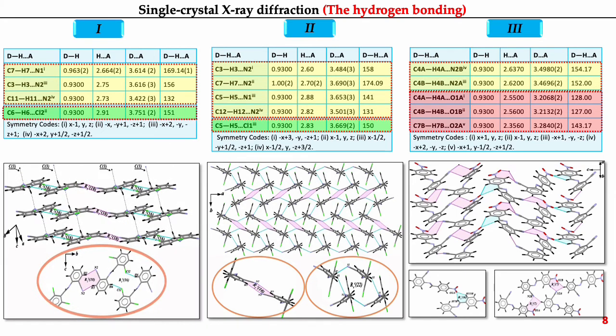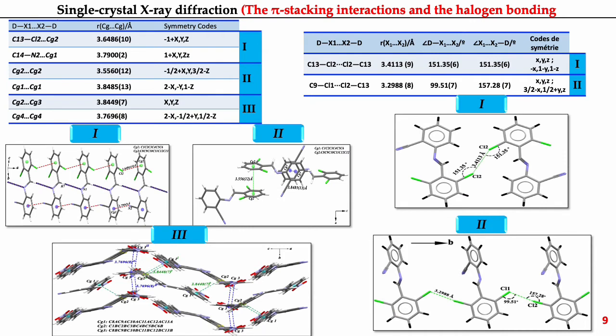The first one is formed by R2210 and R2216 ring motifs and the C3 infinite chain. The second one is based on R2210 and R4422 ring motifs, while the structure of compound 3 is formed by an alternation of rings with R227 and R216 motifs. The crystal structures are enhanced by C-Cl...pi interactions for the first compound and by pi-pi interactions for compounds 2 and 3. In addition, the presence of chlorine atoms in 1 and 2 generates another type of interaction, which is halogen-halogen.